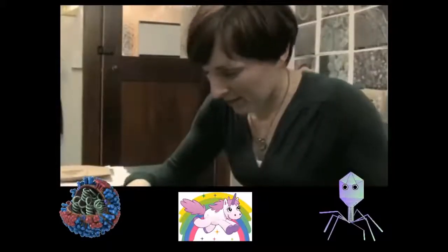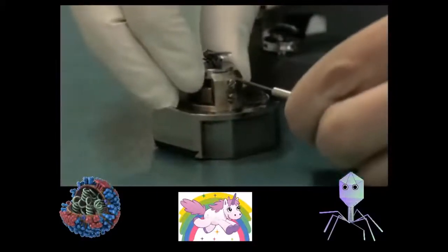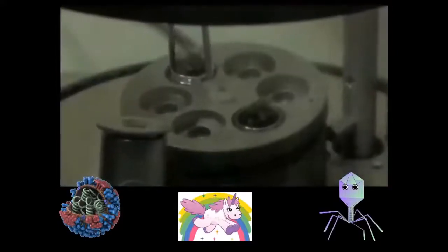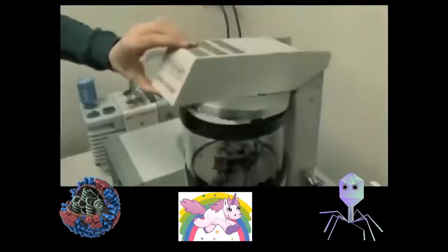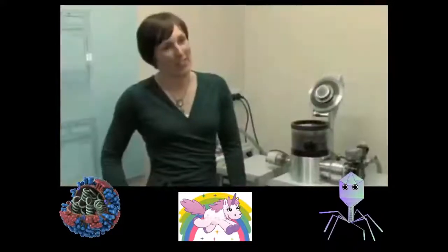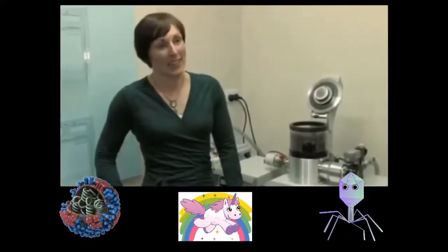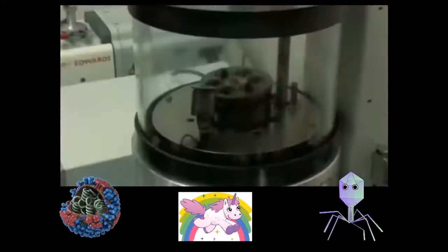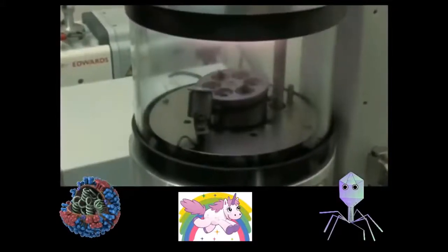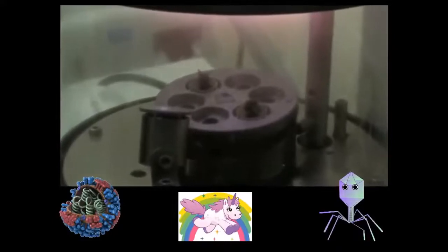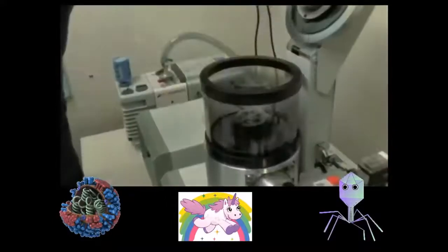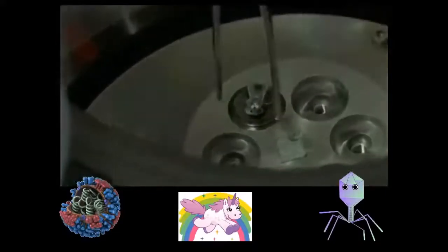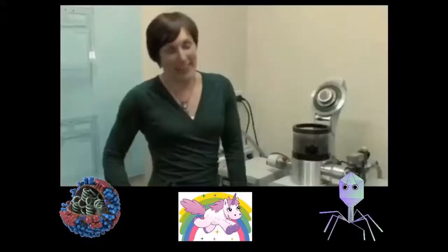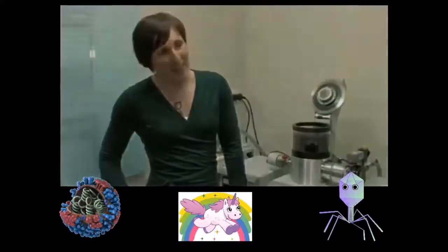So we'd get our sample, attach it to a holder so it's attached quite firmly. We'd load it into the sputter coater, shut everything up and create quite a high vacuum in the coater. We would then pass a voltage over the top of the coater where the metal target is sitting, and that creates a little electric field inside the coater itself. We then bleed gas into the chamber. The gas molecules get all excited and they kind of hoon around and knock little bits of the target material off. So those little bits of the target also move around inside the chamber quite randomly, and they find their way and land on top of the sample, creating quite a thin layer.